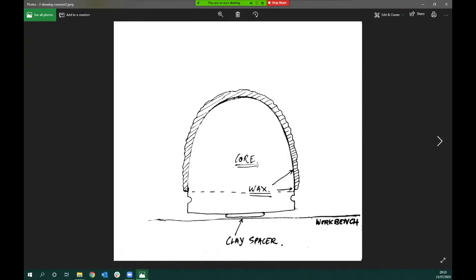Around that central core, we then dip the wax, and it's a bit like candle making. If you start with a wick, you can then dip repeatedly into a molten pot of wax and it coats the surface. So in this case, we're just coating the core with a layer of wax over the top. And then obviously how far we dip in depends upon where the object is going to finish.